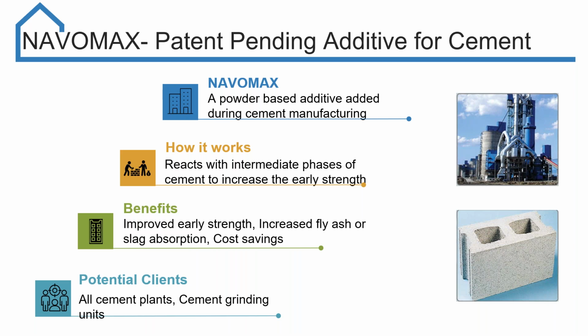So once again, as I told you, it's a powder-based additive. It reacts with the intermediate phases of the cement to increase the early strength and later strength. And I'll explain why. What happens when you increase the SCM in your cement or concrete? All these supplementary cementitious materials, which are basically slag or fly ash, contain from 8 to 30% of alumina.